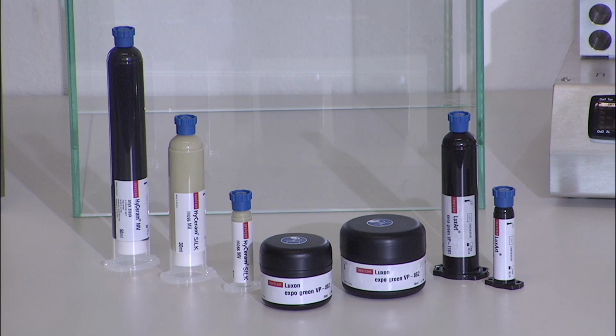It doesn't matter if it's Luxon or LuxArt, it's always the same with light curing materials. So please, always, if you use these materials, check on our website. There is a color chart, and under each color you can find the maximum color thickness of each color. With HyCeram, of course, you don't have this, which is a little bit of an advantage, because with HyCeram you can put as huge a layer as you want. So there is no problem with any colors. You can use black or whatever, or brown, or pearl colors, and there is always one layer.